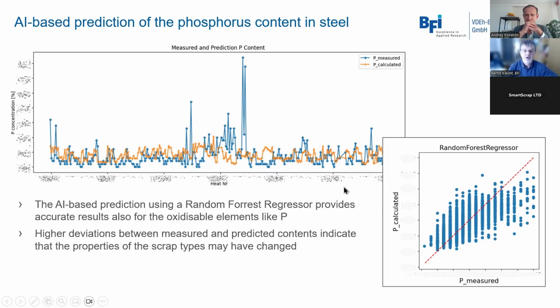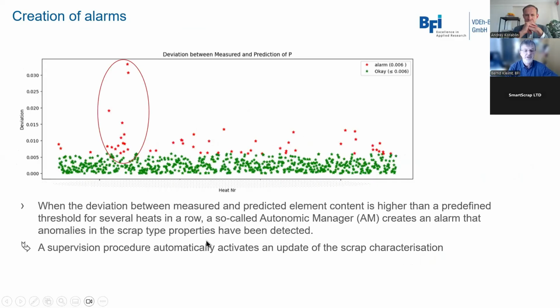And when we do this comparison more systematically, and in case we find that this deviation between measured and predicted element content is higher than the predefined threshold for several heats in a row, which is indicated, for example, here, where we have several heats in a row with a much higher deviation than the average, then we use a so-called autonomic manager, which is also an artificial intelligence tool, to create an alarm that anomalies in the scrap type properties have been detected.